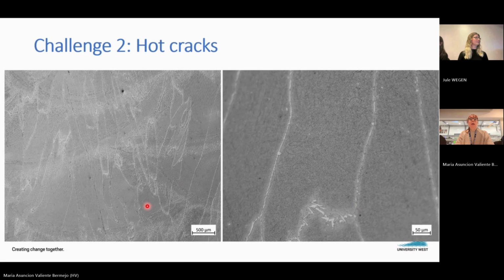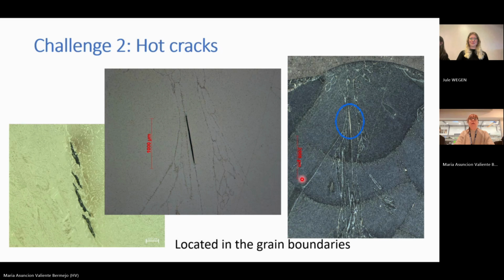And also we saw, of course, in the areas where we were reheating and suffering from this heat, we found some secondary austenite and, interestingly, a lot of epitaxial growth. Some grains were progressing, we could identify the same grain, towards 1, 2, 3, 4 layers. So it was really long grains, as I will show you now, here on the right. These grains were super, super long.